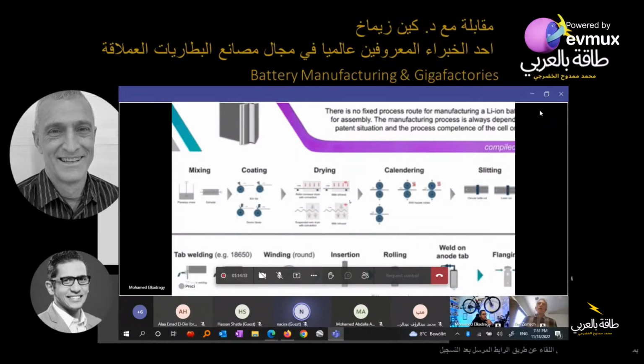That is true, but there are, like I said, always exceptions. For instance, LFP, which is iron phosphate. It's a different type of cathode. There are many manufacturers that actually do their cathode using water. They do an aqueous process for two reasons. You say, wait a minute, Ken, you just said you can't do aqueous for the cathode. For two reasons: because you need a fluorinated binder to be electrochemically stable, and secondly, your lithiated cathode is too sensitive to water.